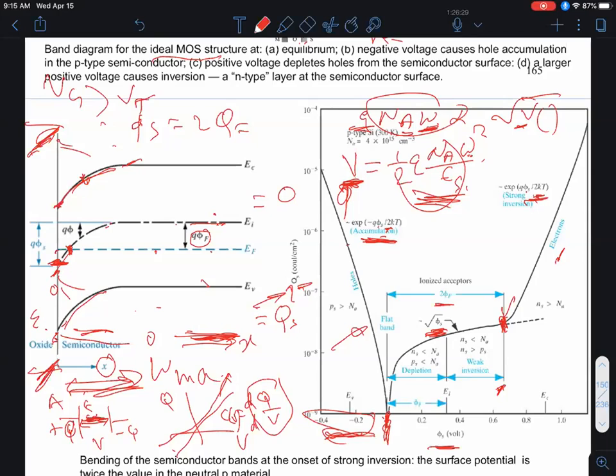Now, this is an important curve because from this you can get the capacitance of a semiconductor, which in general we saw is given not by Q over V, but dQ dV. In other words, the slope of these curves. Meaning therefore that in the accumulation region or inversion where the slopes are steep, the semiconductor capacitance is high, while in the depletion region, it's a gentler slope and it'll vary as d square root of phi s over d phi s, or 1 over square root of phi s. Okay?